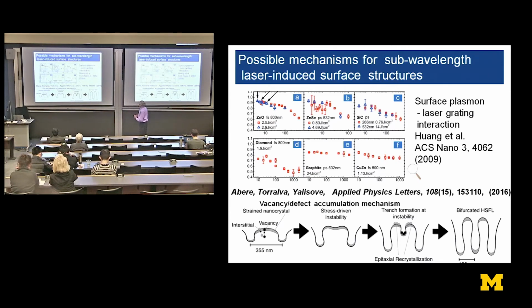For example, this paper by Huang in ACS Nano, it's a highly cited paper, talks about a coupling between surface plasmons and the laser grating. In other words, the optical field of the laser produces coherent fringes on the surface of the material. The laser produces a plasma, as I've discussed. That plasma can couple to the optical field of the laser, and it can produce additional periodicities and length scales that are more appropriate of the surface plasmon length scale, which is much shorter than the laser wavelength.